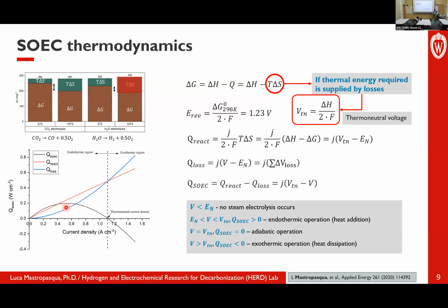If you increase the current, your electric circuit will start producing more and more heat through Joule heating. So your endothermic reaction will be compensated thermally by the Joule heating. There is going to be a point, over here, at a certain current, where the system becomes thermoneutral. You have all the endothermic processes compensated by the Joule heating processes. That is the so-called thermoneutral current, or the thermoneutral voltage which corresponds to that current. Beyond that point, the system becomes exothermic. The Joule heating will more than compensate the endothermicity of the reaction, and the system will start producing heat.